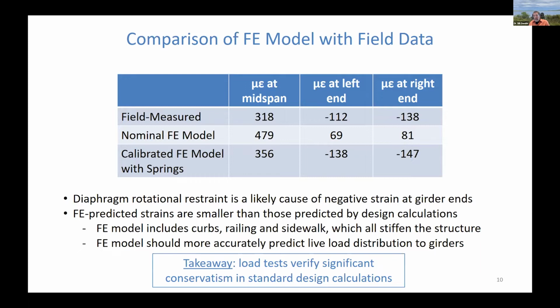So we took a really deep dive into this data. We looked at it very closely, but the important message here, the real takeaway, which is in the blue box, is that those field live load tests really verified conservatism in our design calculations. So as we would hope and as we would expect, the first instance where this girder was put into service is a conservatively designed structure. We have not only redundancy in it, but we also have other load carrying mechanisms that are helping us out. They're nothing we would count on in design, but they're there, they're real, and that's always good to know.